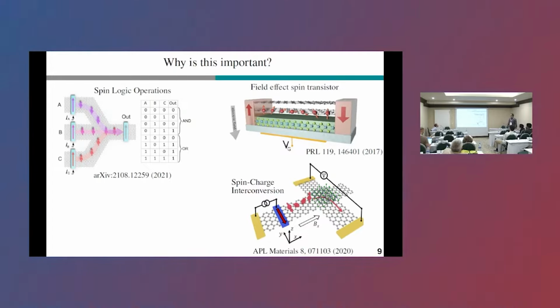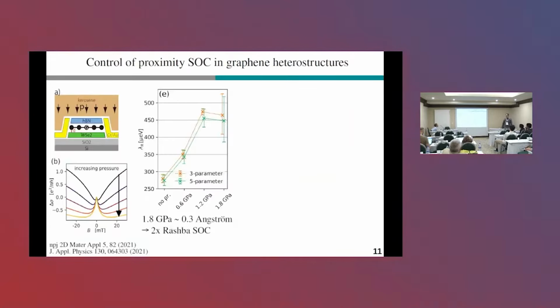Now this is very nice, but still we would like to know if we can get another handle on this and somehow control things a bit more. So we would like to have an on-demand control of these spin interactions and optimize things for spintronic devices. One way to do so is via external pressure. For example, in these experiments it has been demonstrated that the proximity-induced spin-orbit coupling can be drastically enhanced by external pressure. So what happens? If you place such a heterostructure in a pressure cell, you will effectively reduce the van der Waals distance, thereby the coupling between the layers is enhanced and also the proximity spin-orbit coupling is enhanced.